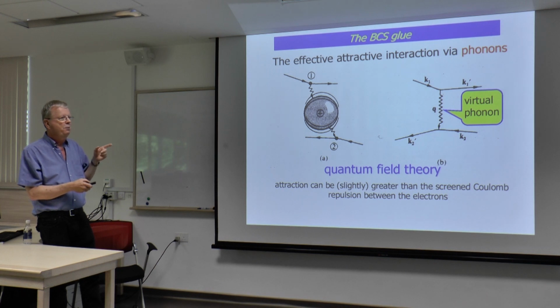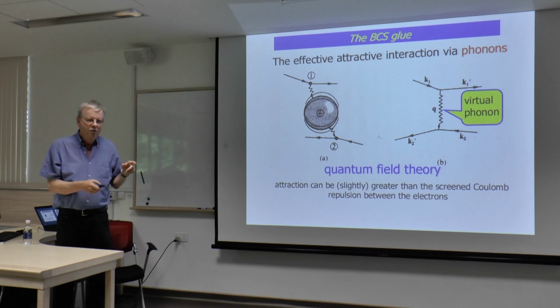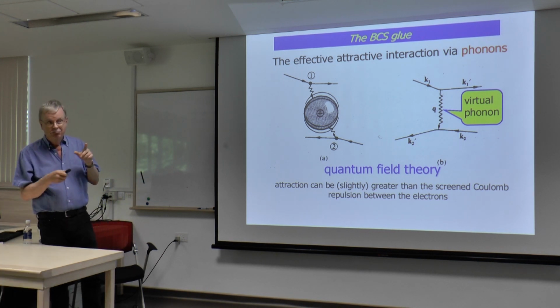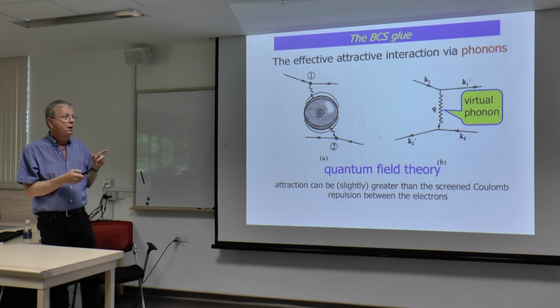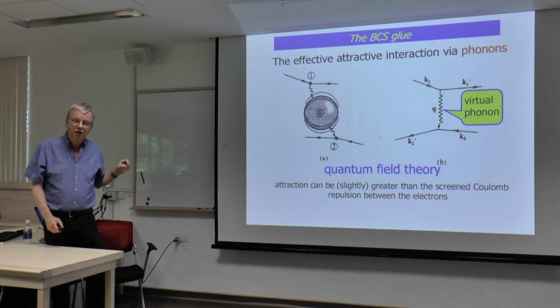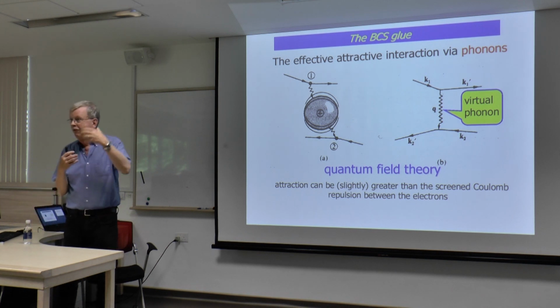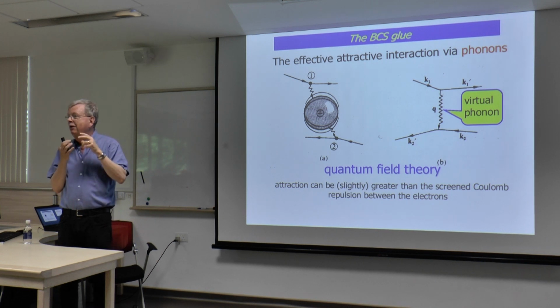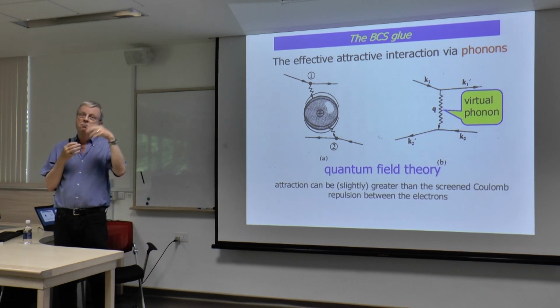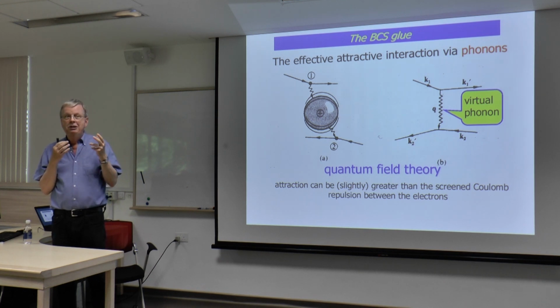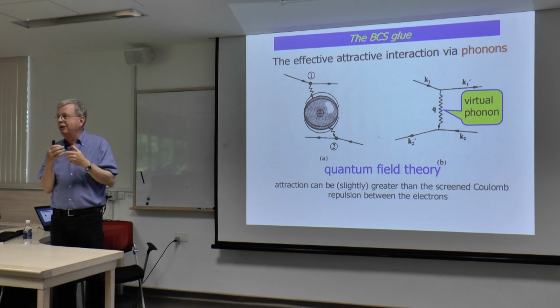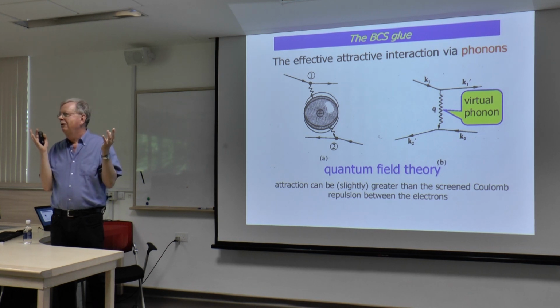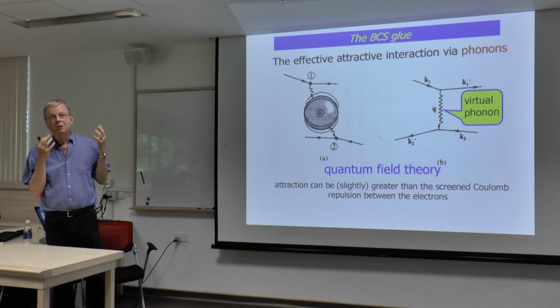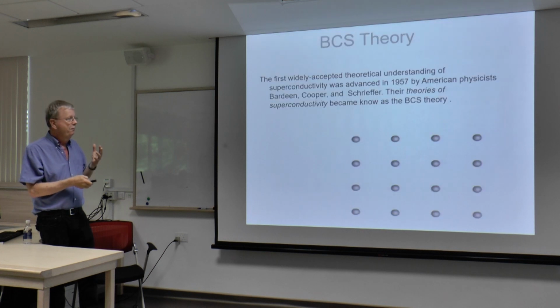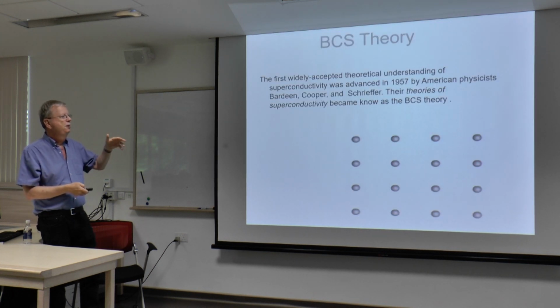Now, one interesting thing, when Steglich came up with heavy fermion superconductivity in 1979, the reason people didn't believe it, Matthias amongst them, Matthias didn't believe it, I think, until his death, was because you saw how one electron distorted the lattice and got out of the way, and the other electron came through and saw an attractive interaction effective to the first electron by the distorted lattice, right? A heavy fermion is heavy, and the electron moves through the lattice very slowly. And so the electron in a heavy fermion system hasn't moved out of the way before the next electron could come by. And so the idea was the attractive interaction there could not be BCS, and in Matthias's mind that ended the discussion, so therefore it couldn't be. Now, of course, if you have an unconventional pairing mechanism like exchange of spin fluctuations, it's a whole other question. Okay? So this cartoon at least serves to describe to you why heavy fermions in 1979 were unusual.